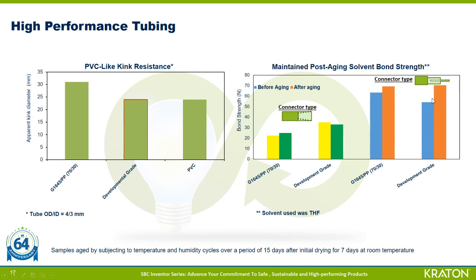So what you can see from this data is that the bond strength depends significantly on the type of connector being used. For example, for this kind of connector where a greater surface of the tubing and connector are in contact to begin with, you definitely see higher bond strengths. Having said that, you can see from this data set that the development grade shows somewhat higher bond strength as compared to G1645 PP blends.